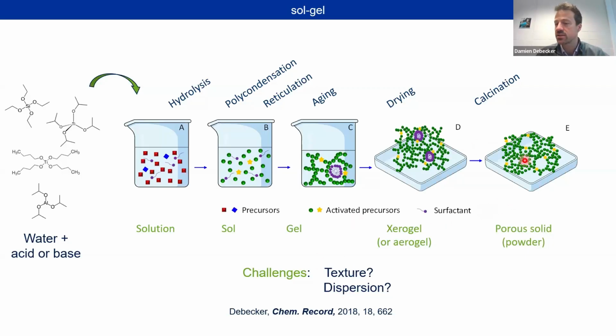The first one is that in catalysis, you need pores. You need to have porosity. So you need to control the texture. And this is classically done by adding surfactant or pore generating agents that, for example, here in this case form micelles, that you can burn away to leave a calibrated pore. There's another challenge that I call dispersion. By this, I mean that very often in catalysis, you will want to have one active element dispersed into another matrix. Let's say, for example, you want to have isolated titanium atoms in a silica matrix.